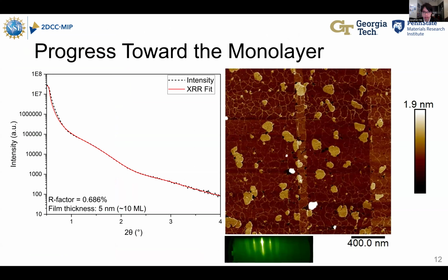This is the result of that growth. We have the selenium first, and we managed to find a time in which these do coalesce into this layer. We did some XRR on this sample. This is our smoothest and flattest sample. It is still around 5 nanometers in total thickness, which is around 10 individual layers. But we can see these individual grains, where you can see the grain boundaries between these different structures, which have developed and then coalesced into this continuous underlying layer.